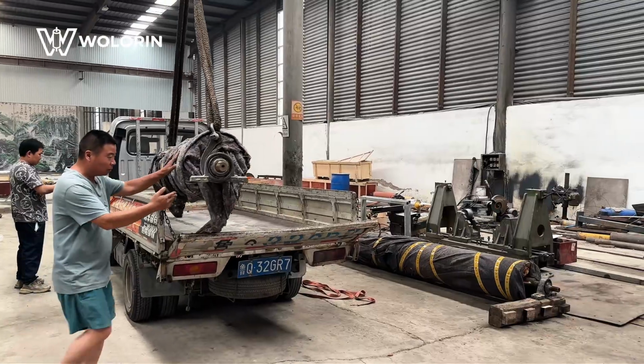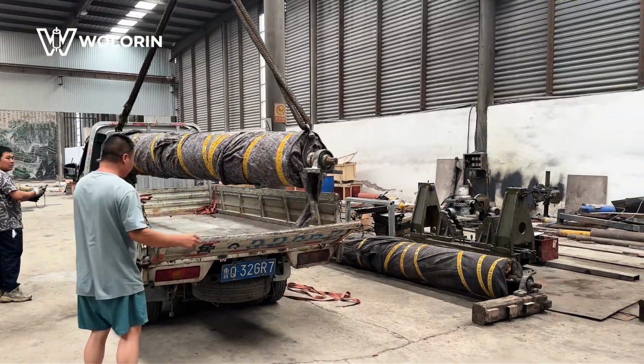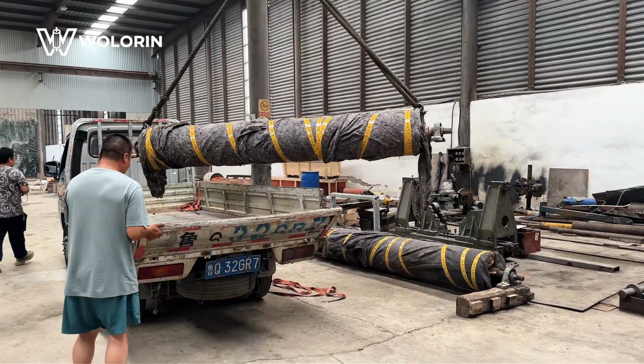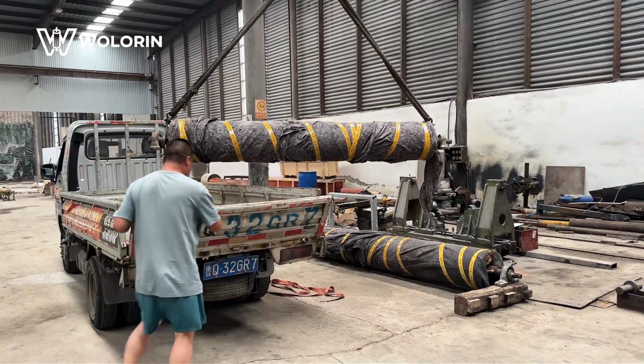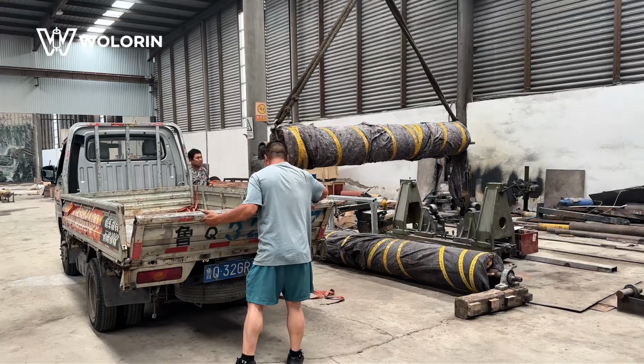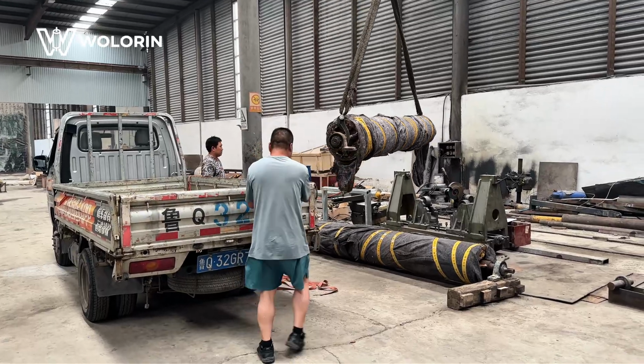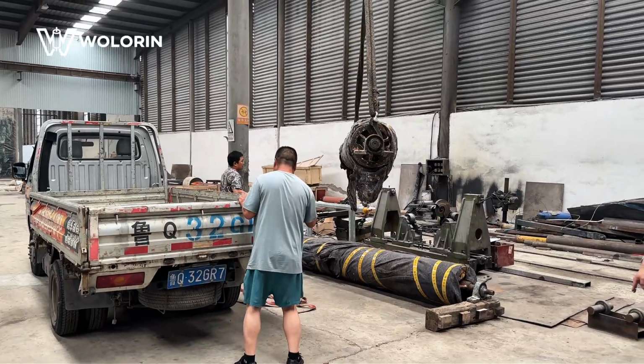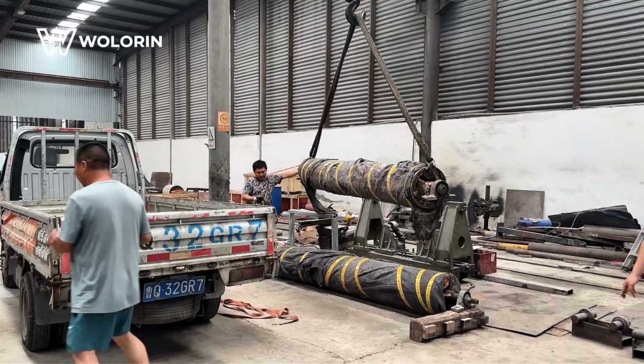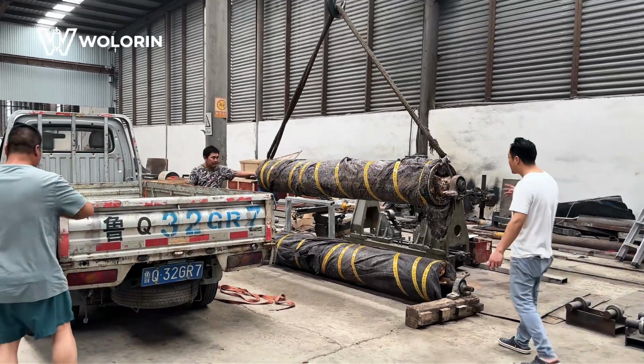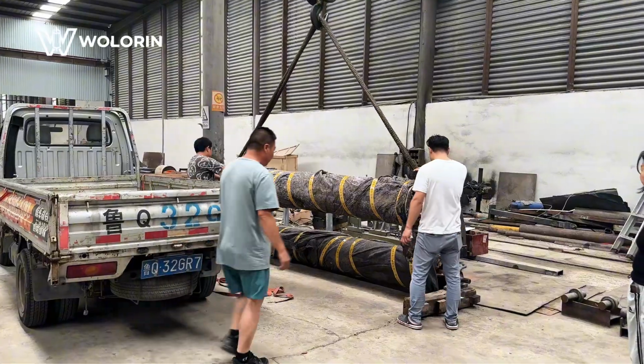If a hot rubber roller remains pressed against the mating roll, it may develop a flat spot even though it runs normally while rotating. For this type of position, the selection should balance operating temperature, continuous pressure, compression recovery, release performance, and the material touching the roller. One material name or one hardness value is not enough.